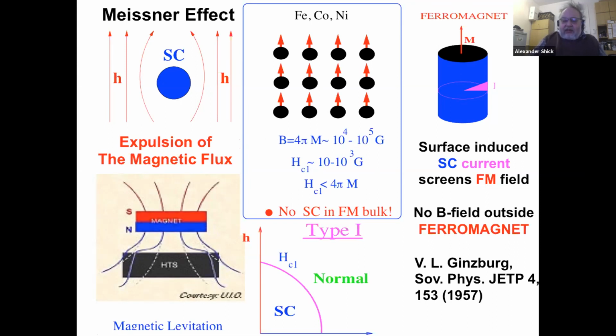Well, indeed, one comment I want to make is that at this time, in 1957, so-called type 2 superconductors were not known, because there are two critical fields. One is the lower critical field, another is the upper critical field. As soon as the magnetic field can go inside of the superconductor, it creates a somewhat mixed phase, with parts of the superconductor in the normal state and parts in the superconducting state. But he was considering only type 1 superconductors.